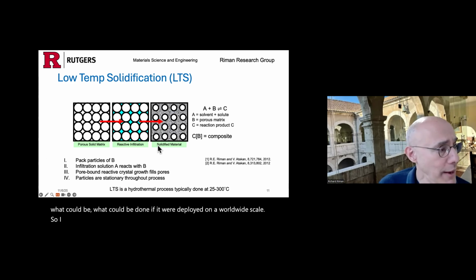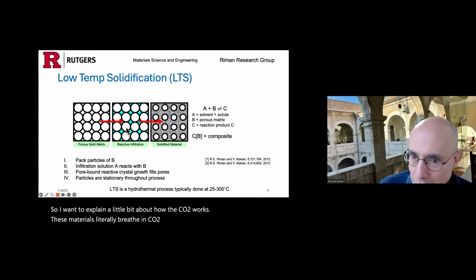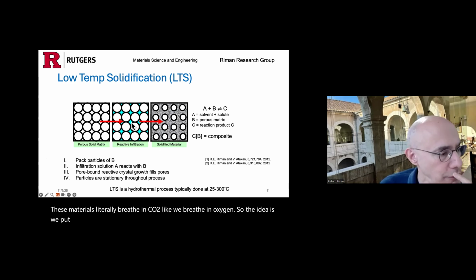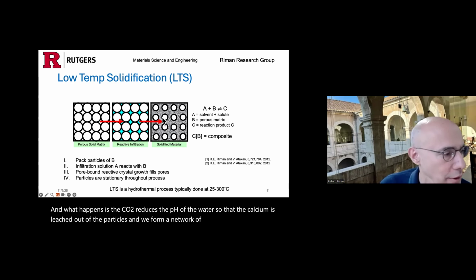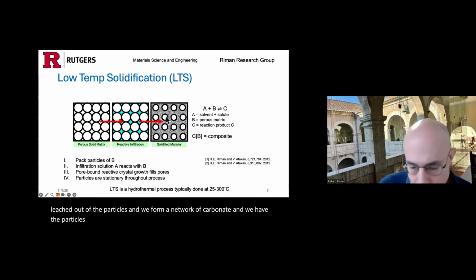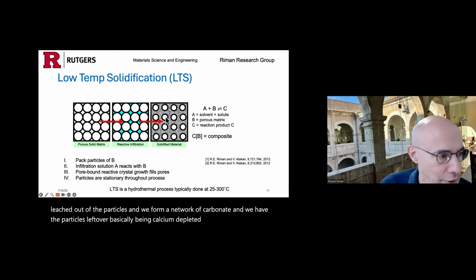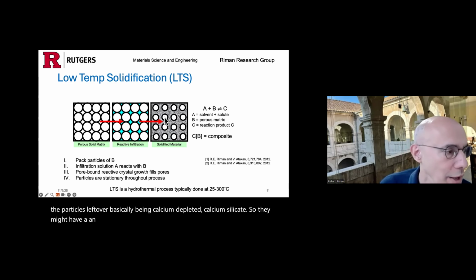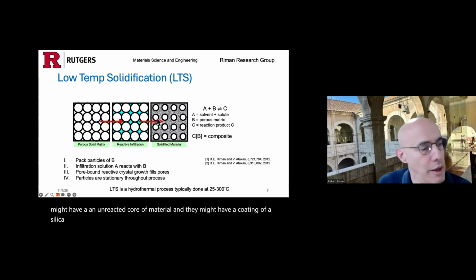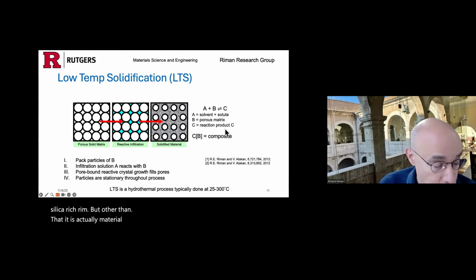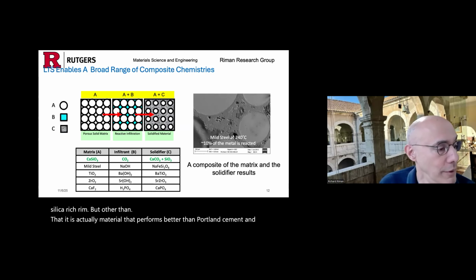So I want to explain a little bit about how the CO2 works. These materials literally breathe in CO2 like we breathe in oxygen. So the idea is we put water in the pores of these cement particles. And what happens is the CO2 reduces the pH of the water so that the calcium is leached out of the particles and we form a network of carbonate. And we have the particles left over basically being calcium depleted calcium silicate. So they might have an unreacted core of material and they might have a coating of a silica rich rim. But other than that, it is actually a material that performs better than Portland cement. And I'll show you that in a moment.